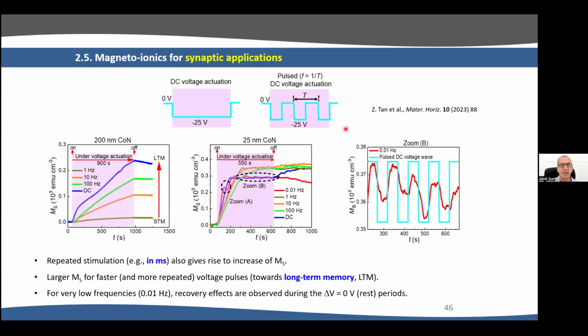And finally, this is one of the last examples I want to talk about, this Magneto-Ionics at fast rates. So here we studied cobalt nitride, and we have 2 films, 200 nanometers, 25 nanometers. Let's start with 200 nanometers. And here the DC is the conventional, let's say, continuous voltage that I have shown you before. But we can also induce Magneto-Ionics applying pulses between 0 and -25 volt at 1 Hertz, 10 Hertz, and 100 Hertz. Now, if we go slowly, like 1 Hertz, you can see that we induce very little effect.